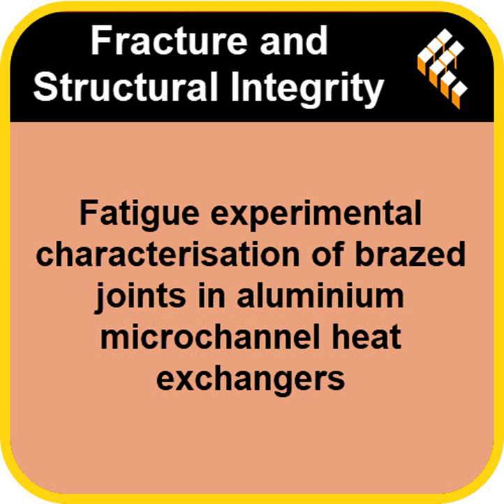One, the original forming process of the base material, whether it was rolled or extruded, because that dictates how it responds to the heat. Right, we saw that strength change. Two, the overall effect of that brazing heat cycle on the base material strength. One gets weaker, one slightly stronger. Yep. Three, the geometry of the joint itself, specifically that fillet toe, which naturally concentrates stress. The unavoidable geometric factor. And four, and this seems maybe the most crucial takeaway from this particular study, these microscopic manufacturing defects. Yeah, the flux inclusions.